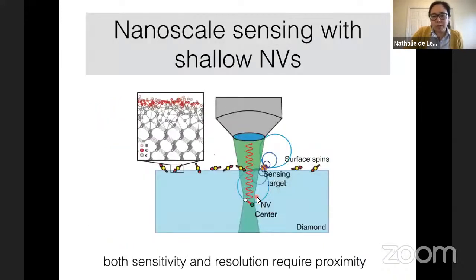So, okay, what are the challenges? Why is it that we have not just deployed this for wide scale biophysics experiments already? In order to take advantage of both this high sensitivity sensor and to get really high resolution, you need to get very close to the target that you're interested in. But if you get close to this sensing target and you're trying to look at anything that's not just inside the diamond, you also end up having to be very close to the surface.